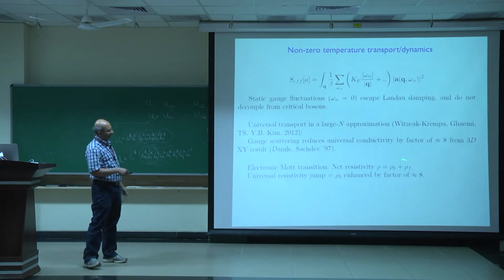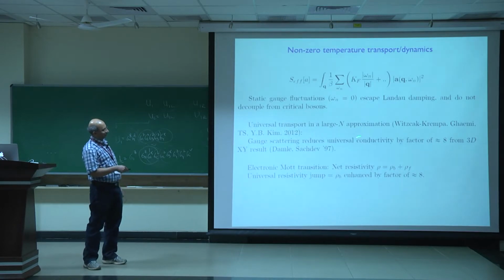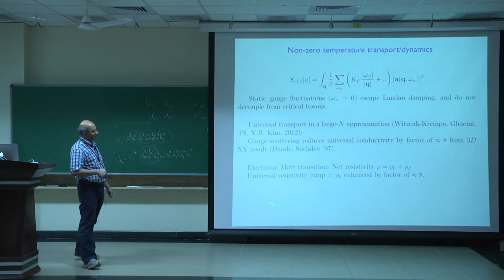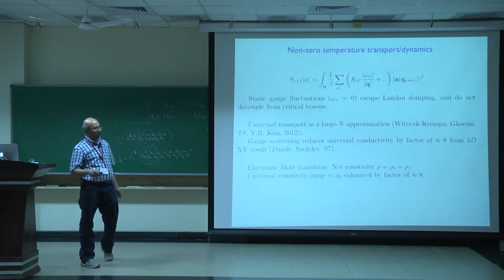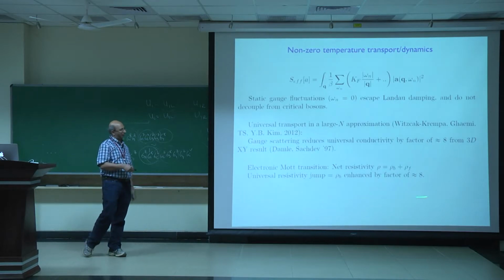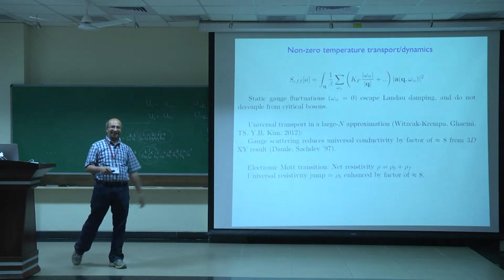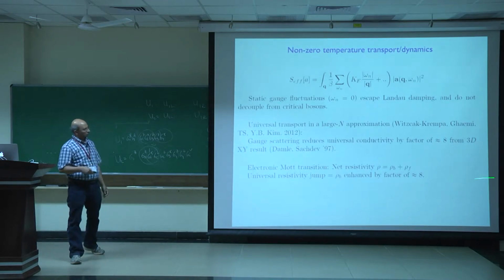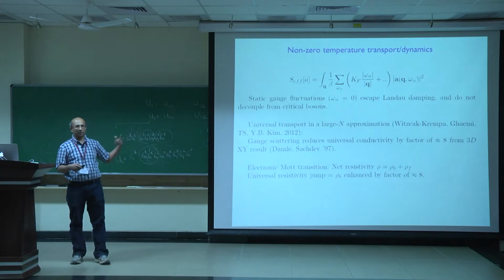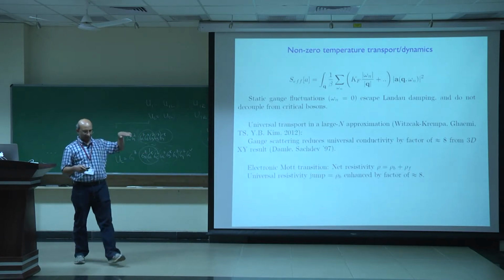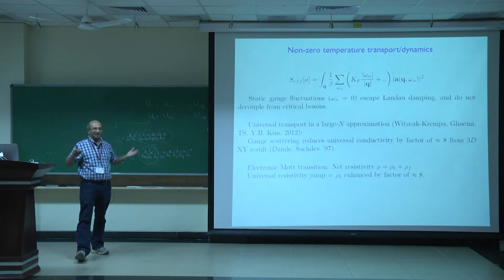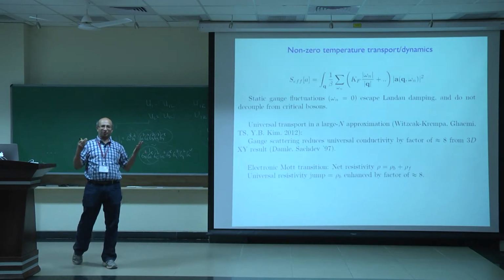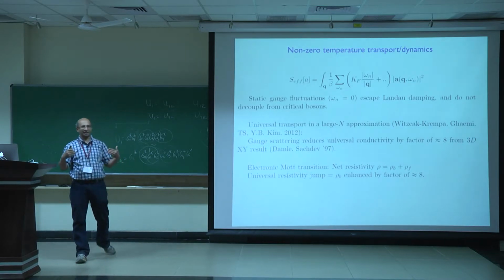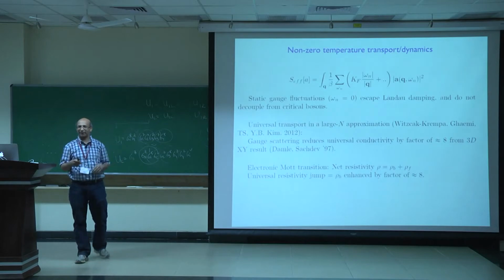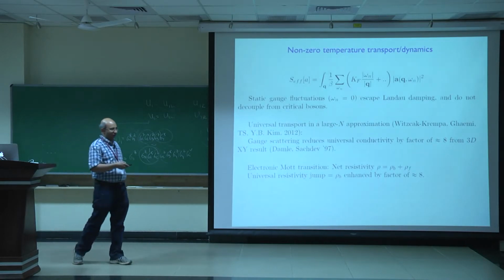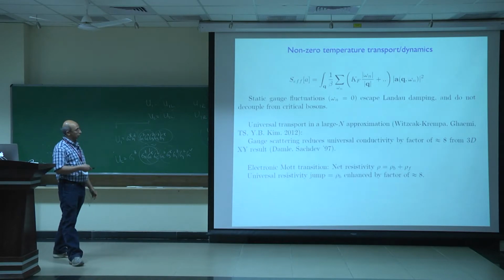Since what jumps is the residual resistivity, and what's reduced is the conductivity by a factor of 8, this means that the universal resistivity jump is enhanced from whatever answer Kedar and Subir found by some factor which turns out to be 8 in the large N limit, right? So the direction is good. So in principle, if somebody did an experiment measuring this universal resistivity jump, they should see a jump that's at least as big as the universal resistivity of the superconductor insulator transition, maybe multiplied by factors of 4. But they should see a bigger jump than what you expect for the superfluid insulator transition of bosons.